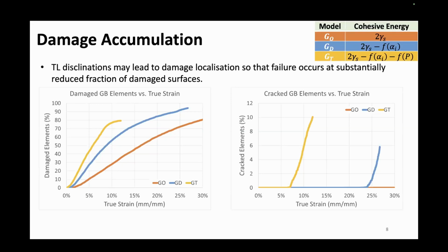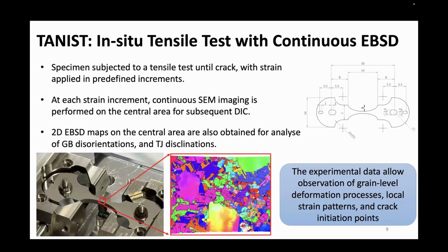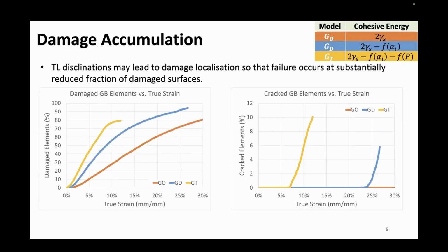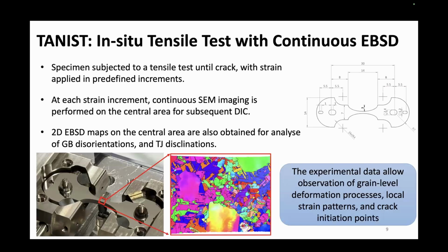So the takeaway from here is that the triple line disclination may lead to damage localization. So the failure starts and occurs at a high rate, with a substantially reduced fraction of damaged surface. So that's our discovery from the simulations, and from those plots and the videos, we can see that the way we consider it in our simulation, whether including disorientation or triple line junction disclination power, has an effect on how we simulate the intergranular cracking.